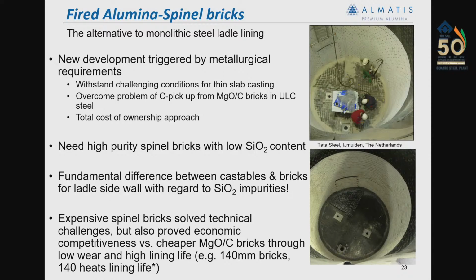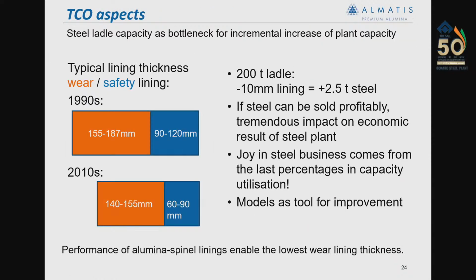Now, I will touch upon some TCO approaches. Another 1 minute I will take. The TCO approach is yet to come or just beginning. Here is the picture. If you see, the blue one is safety and this is the working lining. By incorporating a better and reliable refractory lining, if we can reduce just 10 millimeters in the available working lining thickness in a 200-ton steel ladle, we can cast 2.5 tons more steel in a single heat. So that makes the steel business more lucrative, right?